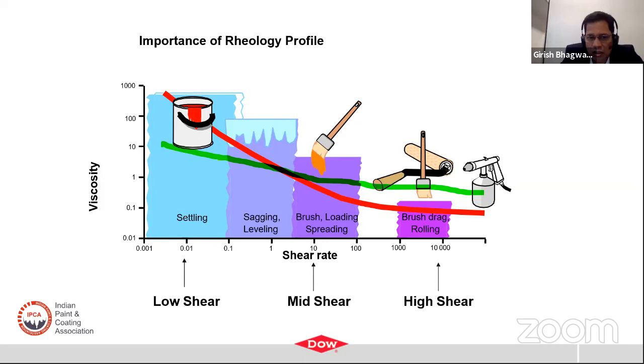Then when you are going to pick it up on the brush or a little bit of mixing, the mid shear viscosity is important. And eventually when you apply it, with significant rolling, brushing, or even spraying, your high shear viscosity is important. So all three viscosities are important that your paint should have. You can't have only high shear viscosity, otherwise you'll have problems in brush loading. So the ideal profile would be the green one, like a near Newtonian.